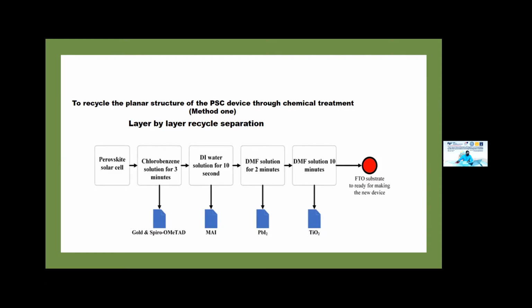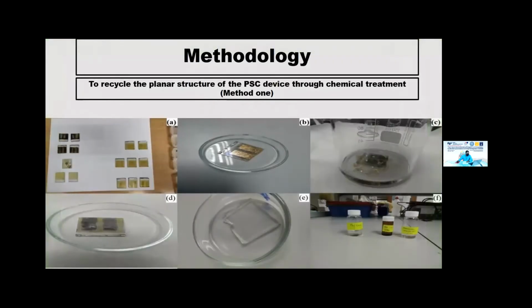use a DMF solution for two minutes, remove the lead iodide. Last but not least, DMF solution used 10 minutes to remove the TiO2 layer, and we successfully recover the FTO substrate. Because in the perovskite solar cell we use FTO substrate, so we can remove also FTO. We tried so that we can reuse the FTO after recycling, recovering all materials. We just keep the glass and FTO substrate and we can reuse it. Is it possible?